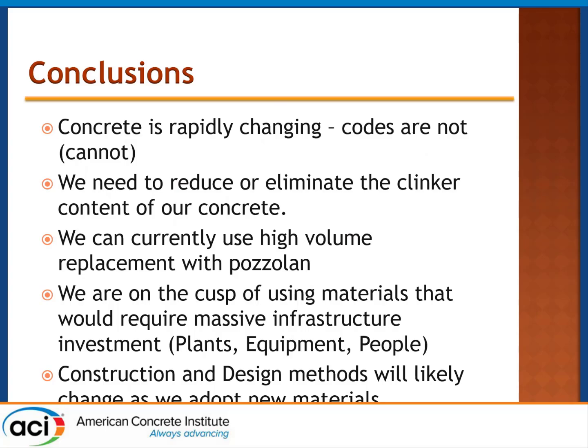Now, concrete is rapidly changing, and our codes and standards are not, and I would argue cannot, change as quickly. We need to reduce or eliminate clinker in our concrete. Well, we can currently use high volume replacement with pozzolan, 85, 90%. I've got structures that are 2 decades old sitting in the Mississippi River without any scaling, without any freeze-thaw damage. So I'm not telling you that I did it in a lab. I made it at 200 cubic yards an hour using conventional plants and conventional people.